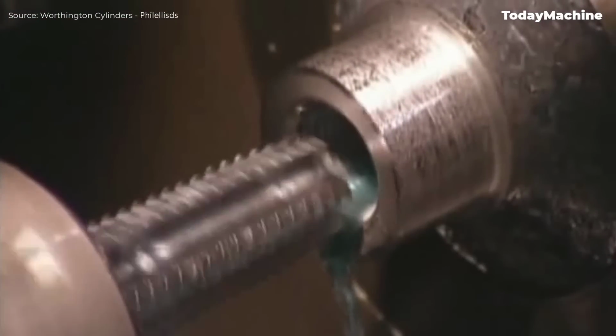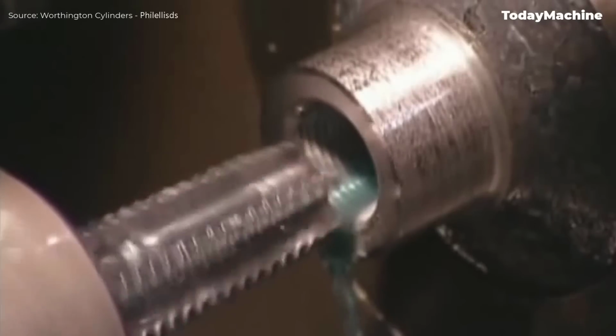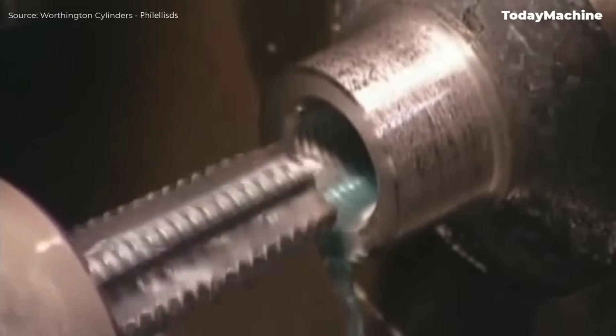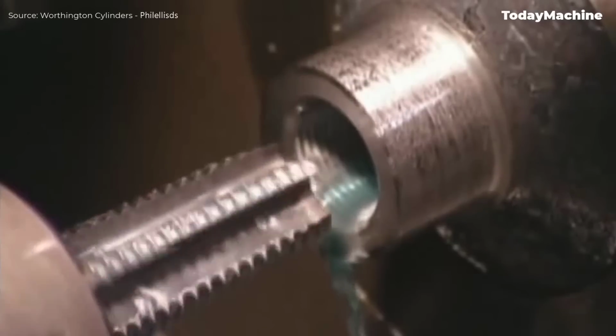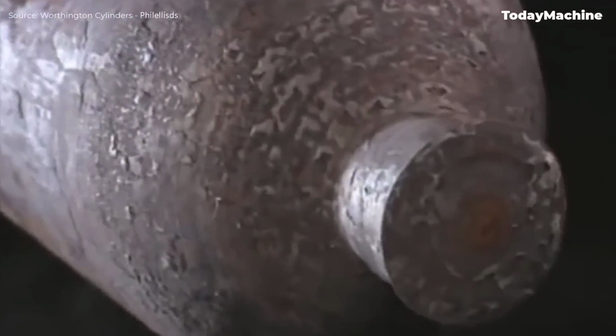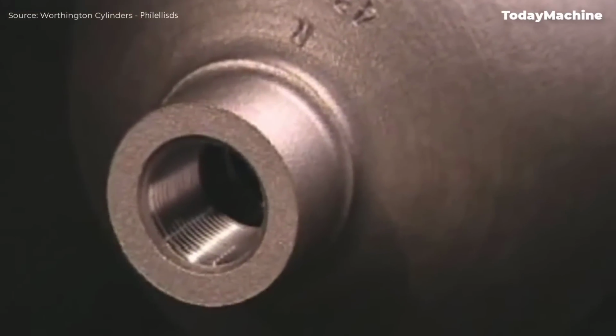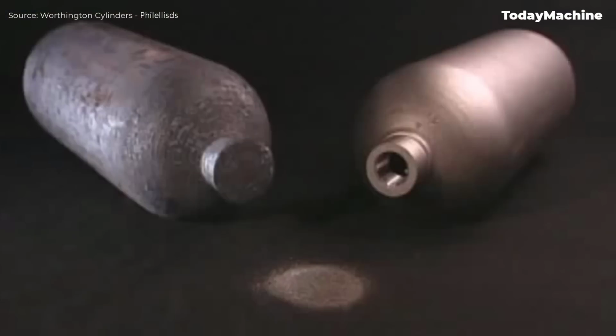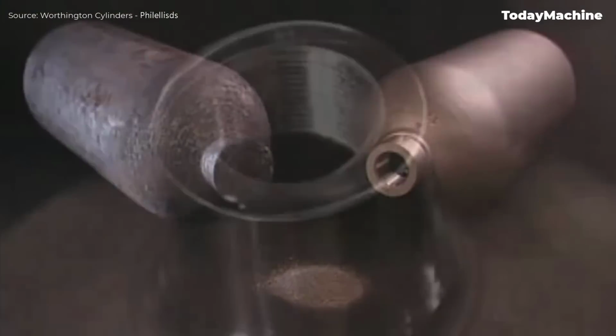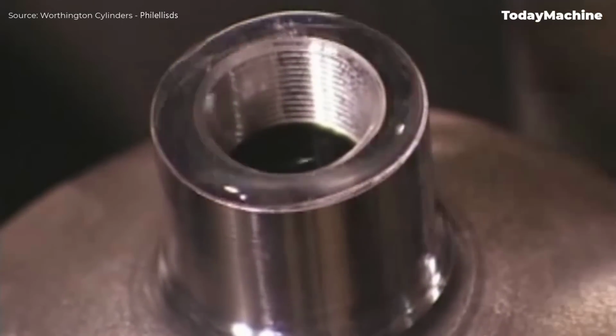Following heat treatment, the cylinders are machined to create the required internal thread and O-ring groove. Synthetic coolants are used in machining to prevent the introduction of hydrocarbons into the cylinders. The cylinders are then shot blasted to remove oxides formed during heat treatment, ensuring excellent surface cleanliness both internally and externally. Testing, marking, and corrosion protection.